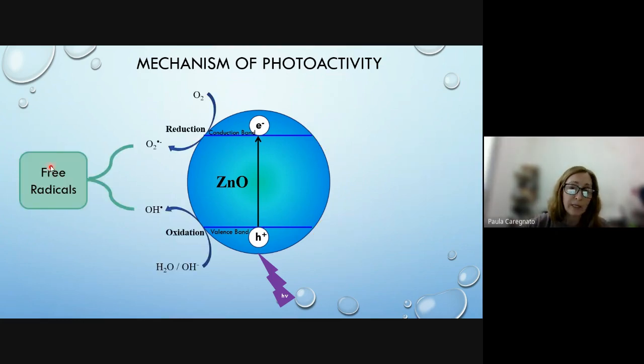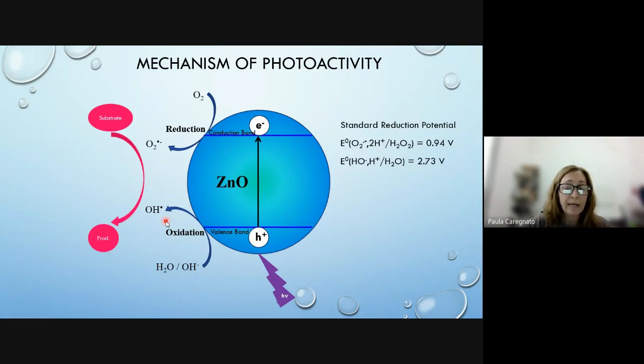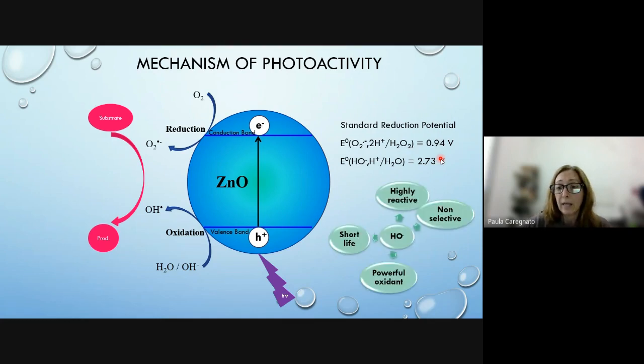In addition, we have the generation of free radicals. When the electron in the conduction band reacts with adsorbed oxygen, triplet oxygen, superoxide radical anions are generated, and when the hole reacts with water, hydroxyl radicals are generated. Those radicals are able to react with the substrate. Looking at the standard reduction potentials of these radicals, we can see the hydroxyl radical is a powerful oxidant. Besides, it is highly reactive, has a short life, and is non-selective.